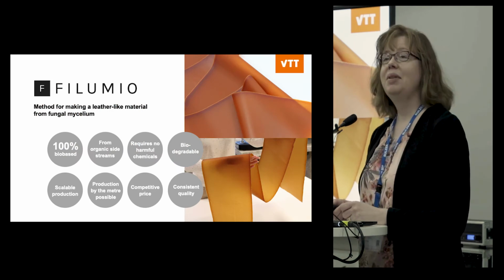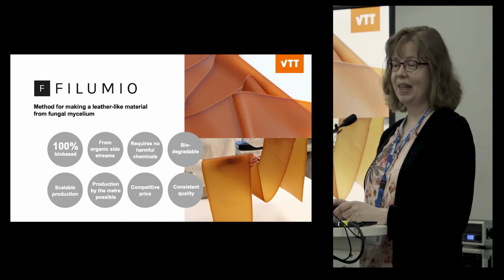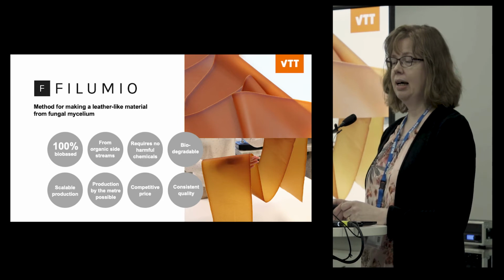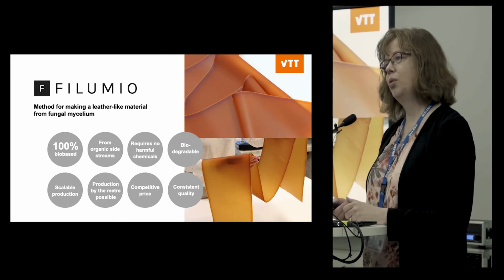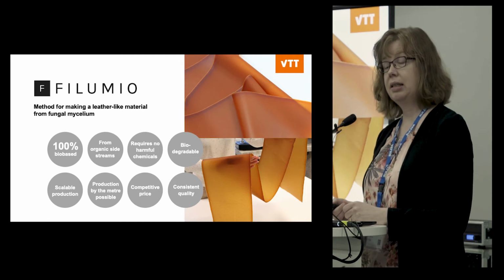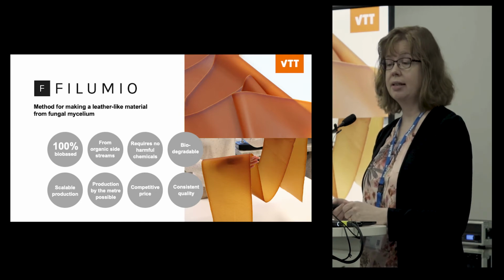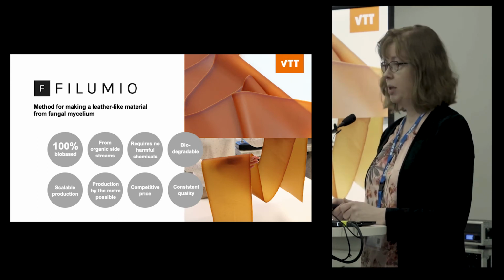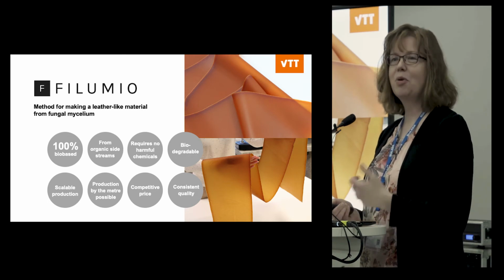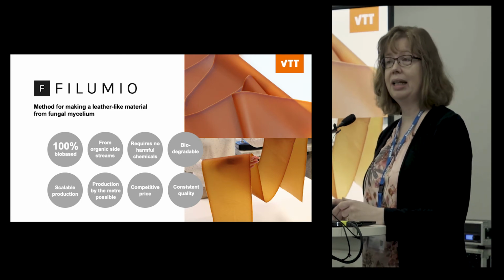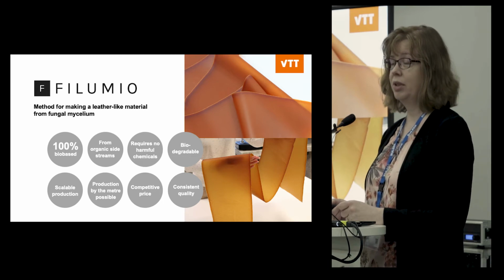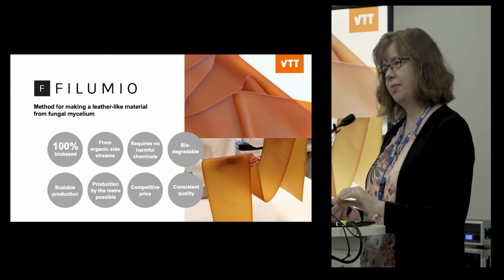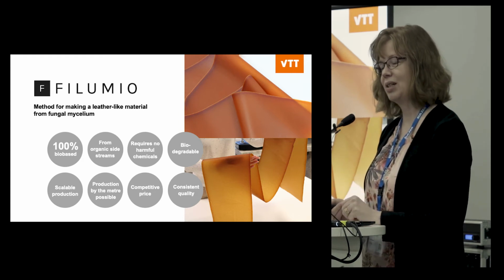We named this material Filumio, and it is 100% bio-based. These examples that I'm showing have been grown on glucose, but we have also tested that it is possible to use different organic side streams as a feedstock. And our production does not require any harmful chemicals, and these materials are biodegradable, so no source of plastics or microplastics.